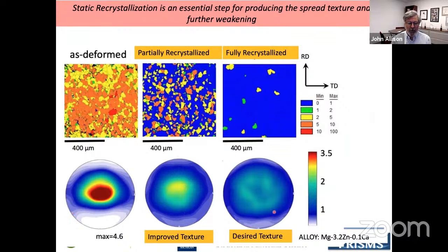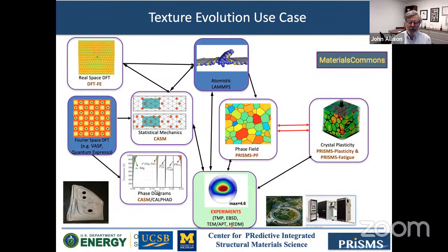However, also very important is recrystallization. This is one of these formable alloys that didn't have quite as soft a texture, but it's still a much reduced texture intensity. But then by recrystallization, this is grain orientation spread from EBSD that shows the amount of recrystallization. So when we have full recrystallization, we can get the desired texture. So that's some work that we'll be doing over the next several years, trying to really understand that. Again, an important part of this will be linking PRISMS-PF and PRISMS-Plasticity directly to do recrystallization analysis.